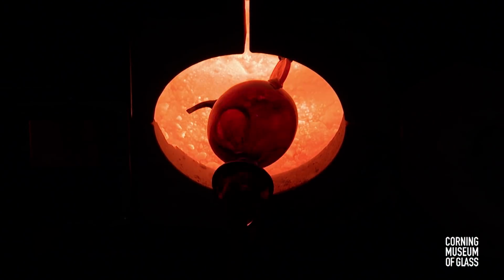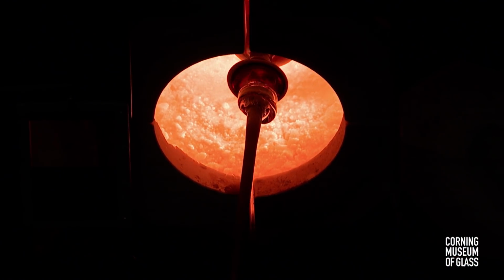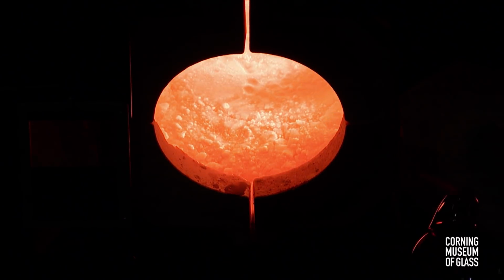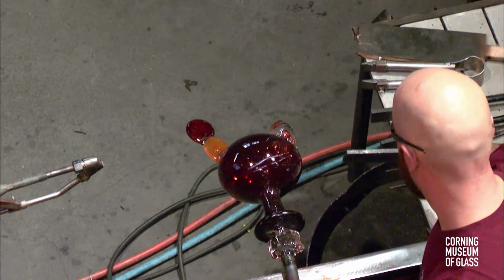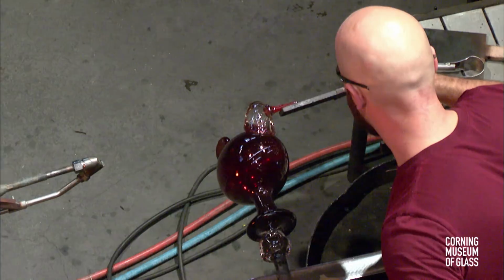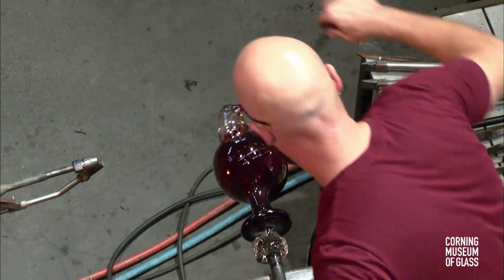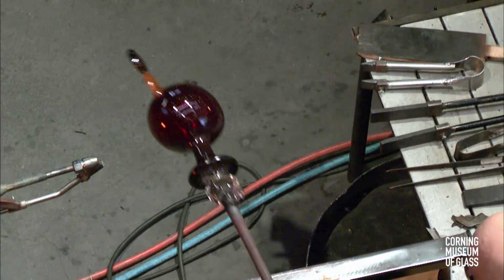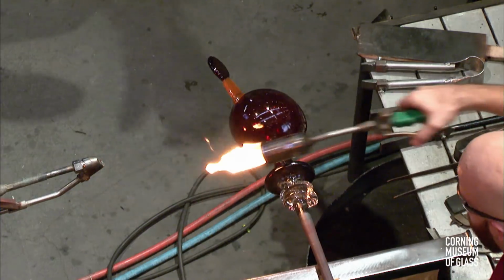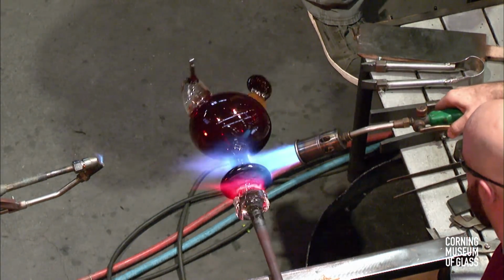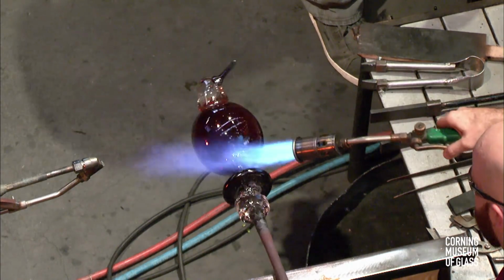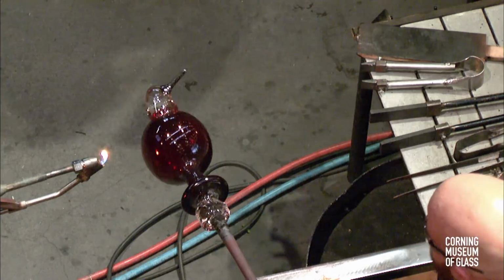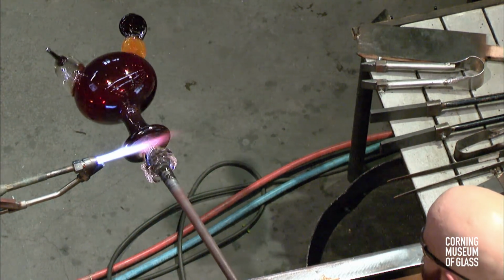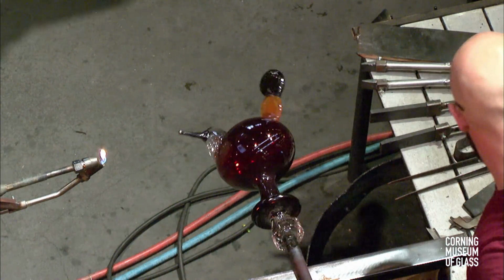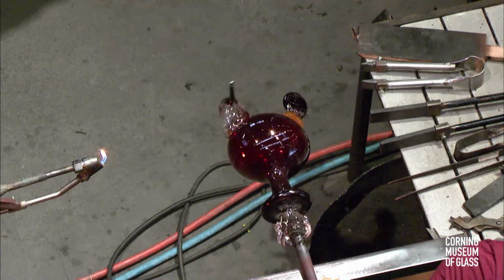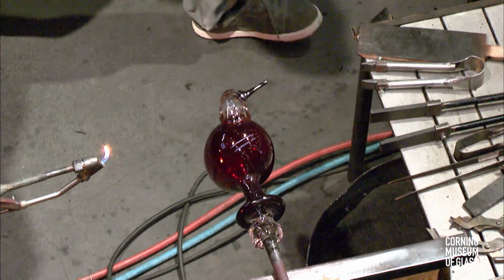You see that we keep going back to this reheating chamber, and this is really just to keep the glass warm. Now, if glass cools too quickly, it's a good chance that the glass will break apart from something we call thermal shock. What's happening is when the glass cools, it's shrinking a very small amount. And if it cools too fast, the surface begins to contract or shrink at a much faster rate than the core. So the glass will break right apart because of that. So everything that we make up here has to be slowly cooled. We call the process annealing, and something this thick, it'll probably only take about maybe 10 or 12 hours. The cooling rate is really driven by thickness, so if it's much thicker, it does take longer. But we're just about ready to break this piece free.